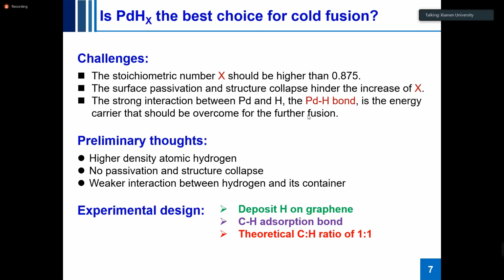So my primary question is, can we deposit atomic hydrogen with high density on other materials, on which there is no surface passivation or structure collapse, and also weaken the interaction between the hydrogen and its container? So the experiment design is we want to deposit the hydrogen on graphene, and in this system, the hydrogen bond should be the adsorption bond. This is much weaker than the chemical bond, and the theoretical hydrogen over carbon ratio is almost 1.